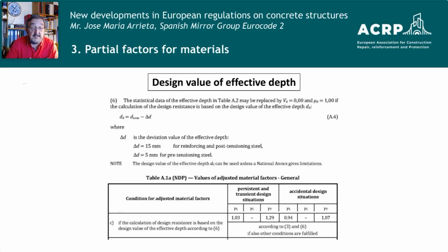If we use this effective value, calculated as the difference between the nominal value and a deviation, which in reinforcing steel is 15 millimeters, then we can reduce the coefficient. For example, you can see the partial factors of the steel, we can reduce from 1.15 to 1.03. All that makes all the partial factors adaptable to each situation, and that obviously reduces the quantity of materials and goes in the direction of sustainability.